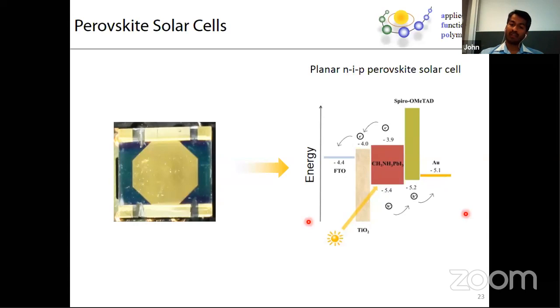Those are electrodes. So when you shine light, or when you place this device in open air or in light, the methylammonium lead iodide, the perovskite, would absorb light and then produce charges, free carriers we call them, electrons and holes. The produced electrons would travel towards the electrode through the N-type material. In fact, that's the reason why we have an N-type material next to perovskite in this case. On the other hand, the holes produced would travel through spiro-OMeTAD and would eventually reach the gold electrode. So upon shining light onto a device, you make free charge carriers, and you make these carriers move around. This is how you produce electricity from solar cells.